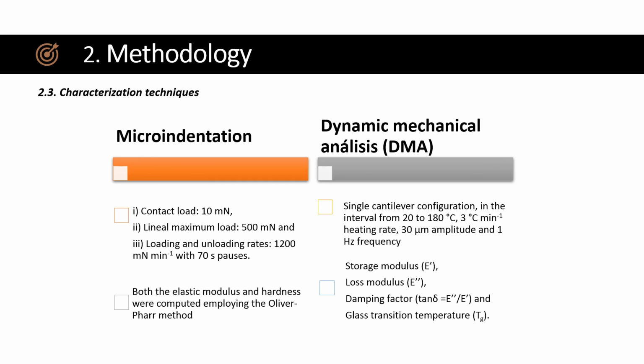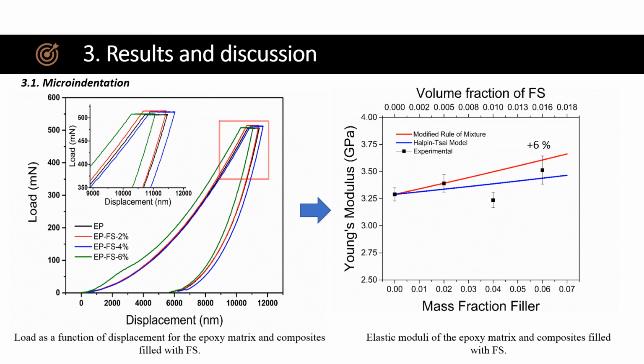On the other hand, dynamic mechanical analysis was carried out to quantify the storage modulus, the loss modulus, the damping factor, and the glass transition temperature. These analyses were performed using the conditions shown on the screen. The results of the microindentation test are shown on the left, and using the Oliver-Pharr method, the Young's modulus of the distinct as-prepared composites are shown on the right.